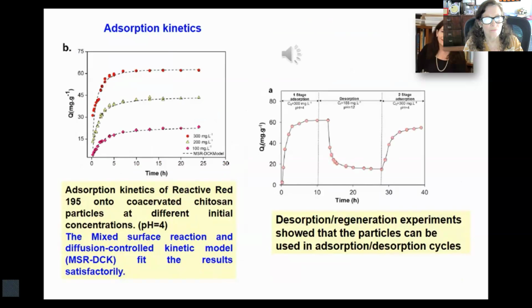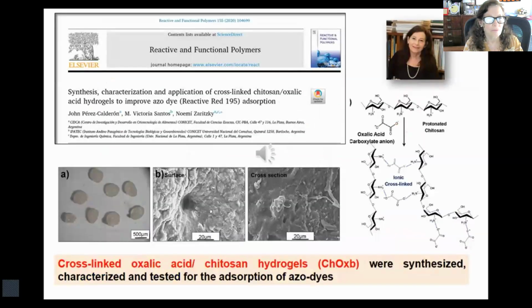The mixed surface reaction and diffusion control kinetic model fit the results of adsorption kinetics satisfactorily. Desorption and regeneration experiments show that the particles can be used in adsorption-desorption cycles. We also synthesized cross-linked oxalic acid chitosan hydrogels that were characterized and tested for the adsorption of azo dyes.